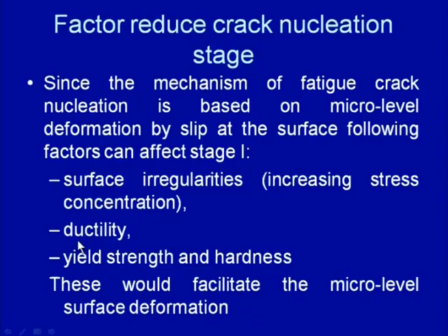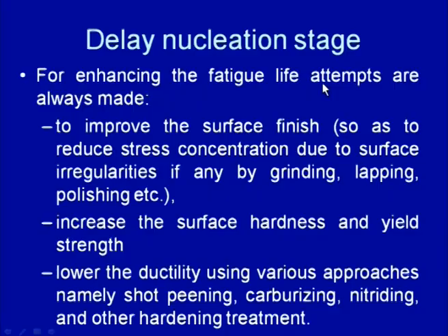So, reducing surface irregularities will help in delaying the surface nucleation stage, as will reducing the ductility and increasing the yield strength and hardness. These will be helping to delay the nucleation stage. So, for enhancing the fatigue life, attempts are made to improve the surface finish so as to reduce the stress